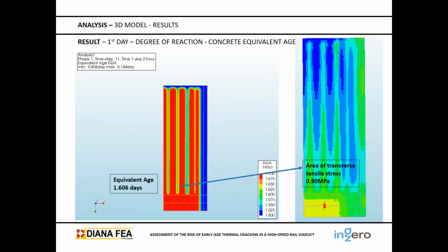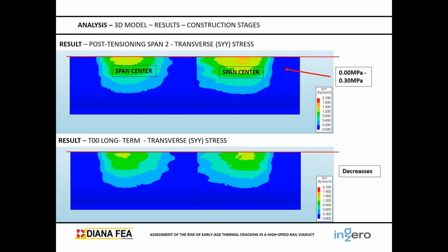We can see it in green in these images, and we have a value of 0.9 megapascals. Also, looking at the degree of reaction, or the concrete equivalent age, in this area of study in which the cracks have appeared, it is 1.6 days. With these values, we can enter the formula to determine the prediction of cracking. We also have a look at the other 3D model, in which we have the whole construction process represented, all the tendons and span by span, and we have the influence of the post-tensioning of one span on the others which have been post-tensioned before.